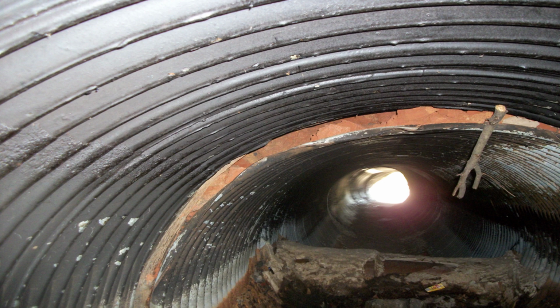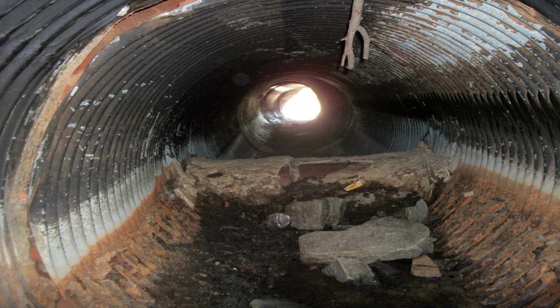They called me and asked me to quote a cementitious lining for the pipe, and when I inspected the pipe, I walked down with a flashlight and looked at the joint, and I could see the underside of the street. I could actually see pavement when I would shine my flashlight up, and the void above this pipe was about the size of a Toyota Camry. You can see in the next picture some other things going on, what actually led to this. You can see the picture of the open joint, and you can also see a clay sanitary sewer pipe that was laid through the bottom of the storm pipe.